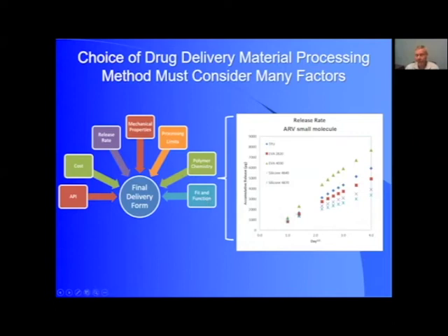So as an example here, I show some internal work that we did with an antiretroviral small molecule using 3 different classes of polymers and some different flavors within those classes. So different silicones, in this case, delivered a slightly lower drug release rate. EVAs had higher release rates, with the TPU that we looked at somewhere in between the 2 EVAs. So you do have, in many cases, a range of choices in your materials depending on what drug release rate you want, and then other ways you can tune it as well.